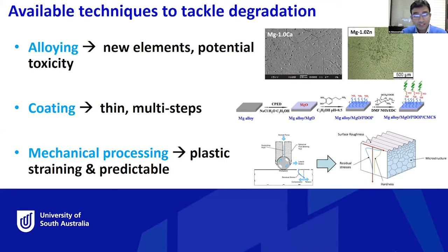The next one is coating. This has been predominantly studied in the literature, and like other speakers have indicated, even Carsten earlier mentioned, people try different types of biocompatible coating, thin to thick coatings, to improve the corrosion resistance. Coating is generally very thin. It could be porous, and there is a potential for breakage and losing integrity. But still, there are some coatings that have been quite successfully developed, and they provide quite a beneficial effect in resisting corrosion.